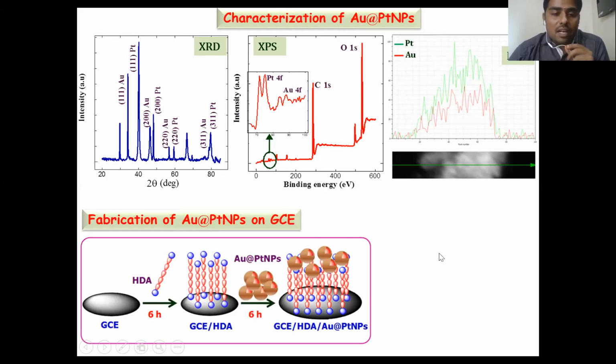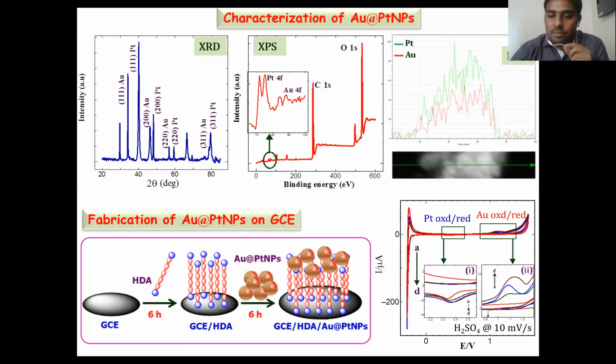The formed gold platinum nanoparticles were fabricated on the electrode surface with the support of a hexadiamine linker, and the gold nanoparticles modified on the substrate were confirmed by cyclic voltammetry in 0.1 molar sulfuric acid at 10 millivolt per second scan rate.